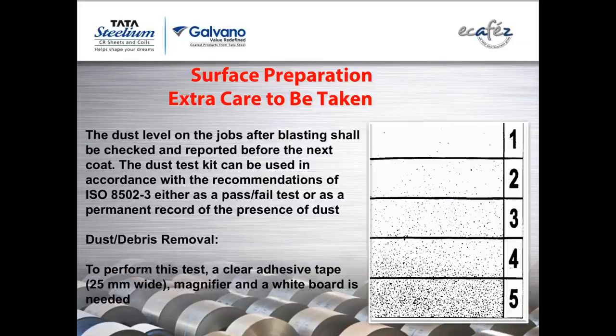Third thing to check again is whether there is dust on the blasted surface. It's a very simple test. You take a clear adhesive tape 1 inch wide, 25 millimeters wide, put it on the surface, just pull it out, paste it on a plain white paper, and on the right there is a chart given. This is from ISO 8502-3, and you compare what is the dust level.